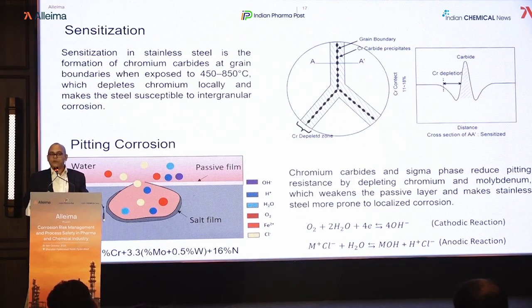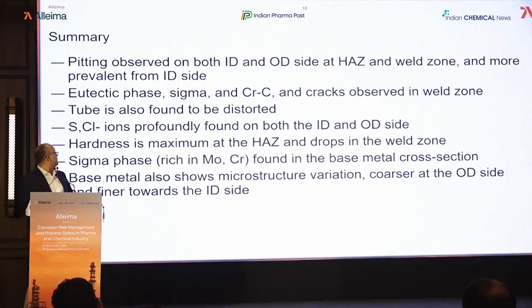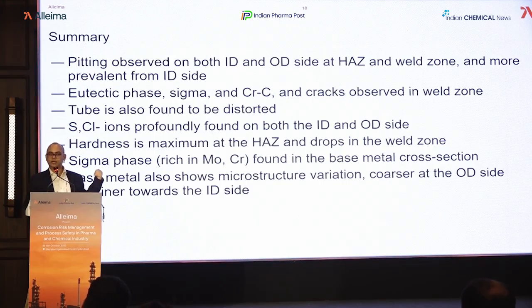That is one way you can say, based on the PREN number, you also select the grade, but that is a crude way, not the exact way. But in general, the higher the PREN number, the better the corrosion resistance. So good. The summary is that with this ERW tube, you will have to be very careful if you are using it. There is a chance that you may have all those intermetallics form in the heat affected zone.